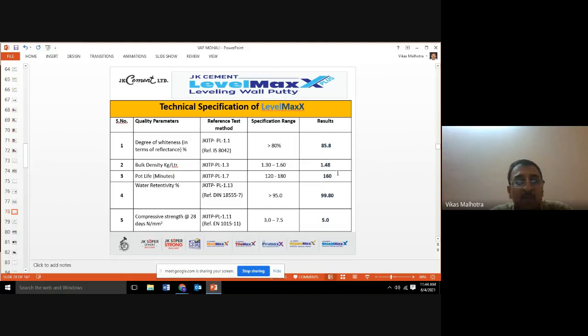So bulk density is 1.48, pot life is 160, water retentivity is very high. When I say high water retentivity, it means it will be acting as a good waterproofing membrane also. That won't allow water to penetrate through it. So if it won't allow water to penetrate, that means this can be used both at interiors as well as exteriors. You can see the strength. If you compare it with normal plaster, normally plaster has a strength of 3 MPa maximum, whereas we are giving more than 5 MPa.